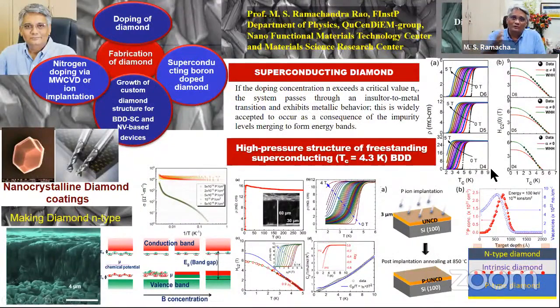If you measure the resistance now all the way down to the lowest possible temperature, you start seeing superconductivity in this. So there's diamond superconductor. So an insulator, upon doping, it acquires a semiconducting property, metallic property, and then finally it becomes a superconductor. But of course at 6K. So then you do the same resistivity measurement in the presence of high magnetic field, varying the field all the way from 0 Tesla to 5 Tesla. Superconductivity doesn't vanish, which means this property indicates that you have a high degree of granularity there. And that is the crux of utilizing boron-doped diamond for many quantum information applications. I'll come to that in a minute. The second part is we also dope diamond with nitrogen. It's not easy, these things, you need to dope these materials.